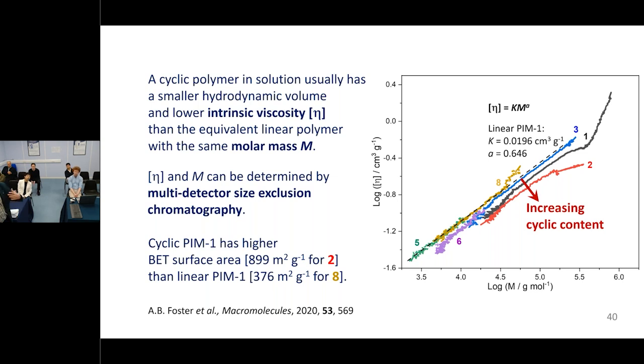In general, both with normal polymers and with PIMs, over quite a wide range, these plots of log intrinsic viscosity against log molar mass will usually be linear. The slope is telling you something about whether it's a random coil or a very stretched out thing, and whether it's a highly branched thing, though branched PIMs behave differently to conventional polymers. But also where something is on that plot varies as you go from a linear to a more cyclic material. So we have ways of telling whether we have a cyclic rich sample or not.